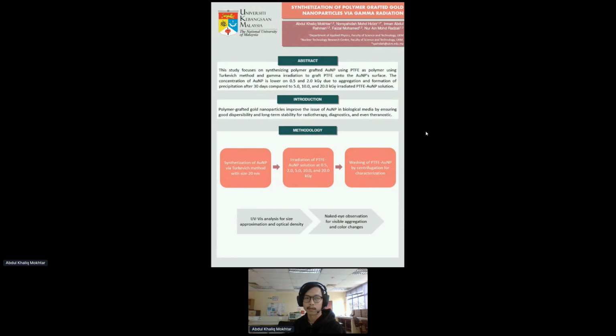What we found is that the concentration of gold nanoparticles is lower at 0.5 and 2.0 kilogray due to aggregation and deformation of precipitation after 30 days, compared to the 5, 10, and 20 kilogray irradiated PTFE gold nanoparticle solutions. Our methodology: first we synthesize the gold nanoparticles via the Turkevich method, and we obtain gold nanoparticles about 20 nanometers in size. Then we add PTFE solution into the gold nanoparticles. After that, we irradiate them at 0.5, 2.0, 5, 10, and 20 kilogray. And lastly, we wash by centrifugation for characterization. We use UV-vis analysis for size approximation and optical density, and naked eye observation for visible aggregation and color changes.